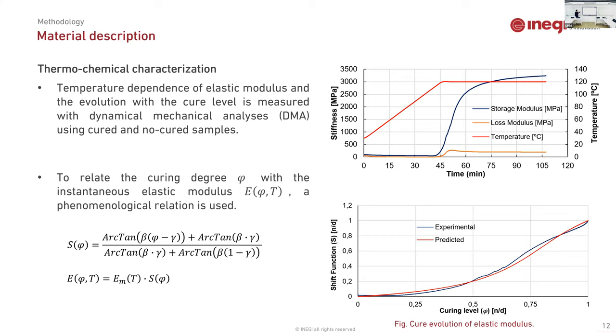How can we do that? For that, it's possible to use dynamic mechanical analysis, where we have a sample of composite or resin, and we apply a load at a controlled temperature and frequency, and we test how the stiffness or the elastic modulus of the sample evolves with temperature and time.